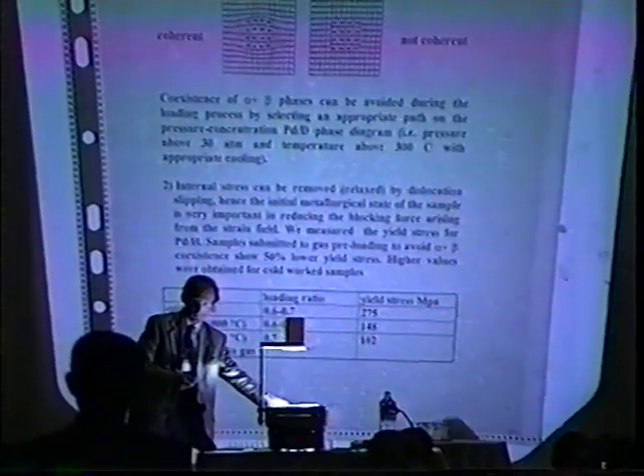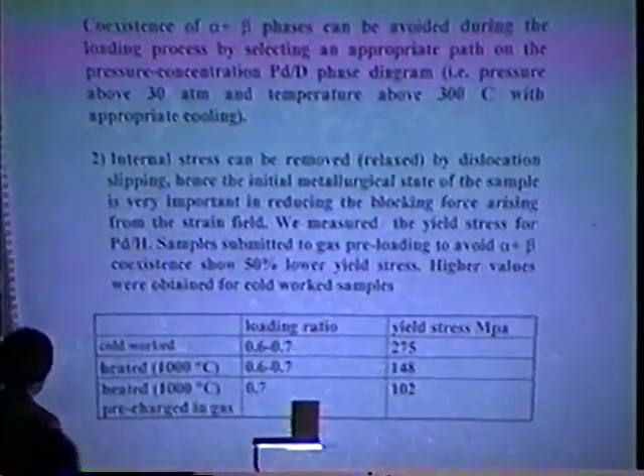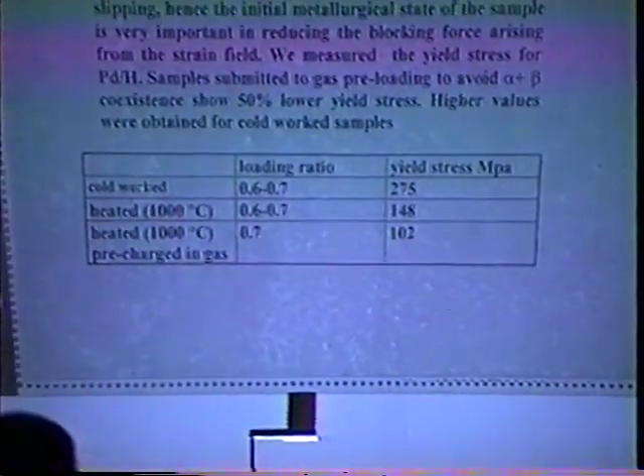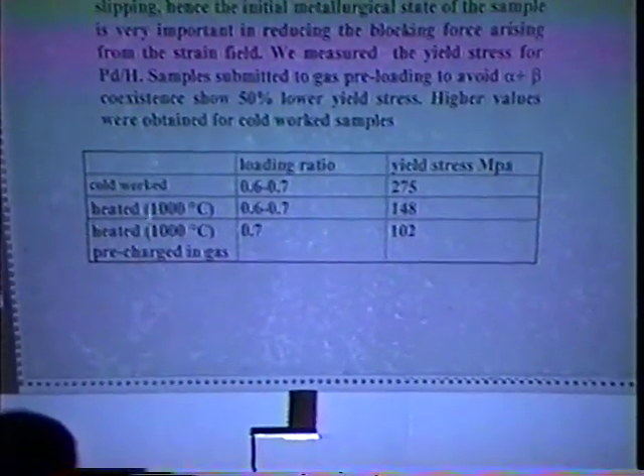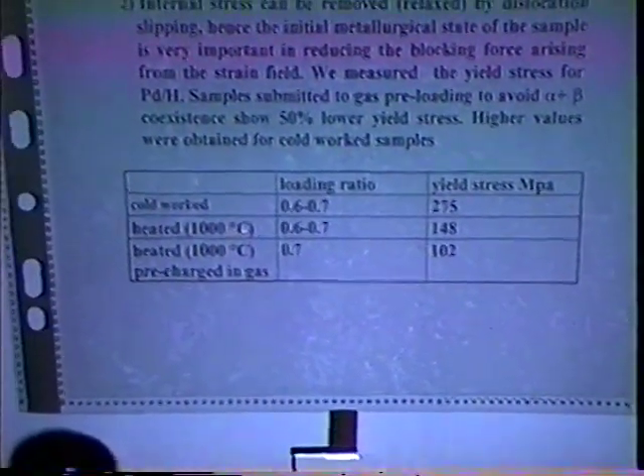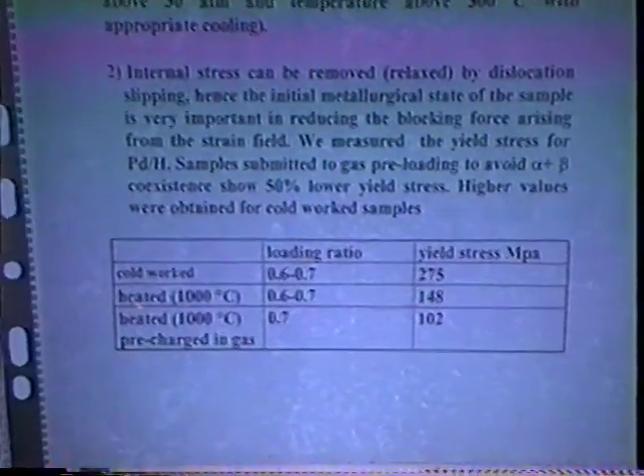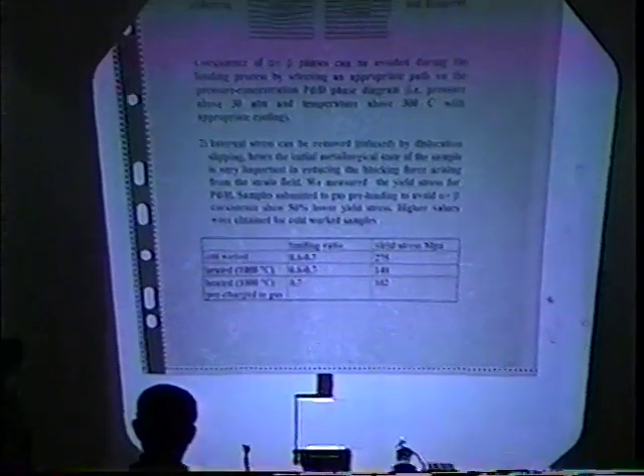In this way, we obtained, first of all, different macroscopic behavior of the medium material after loading. As you can see, the yield stress for cold worked material loaded up to 0.7 is 275 megapascal. When we heat the system at 1000 centigrade and after we load at 0.7, the yield stress is 148. This value is the average of medium measurements. And when we heat up to 1000 centigrade and we make the pre-charge in gas as I showed you before, the yield stress reduces to about 100. So there is a macroscopic difference.